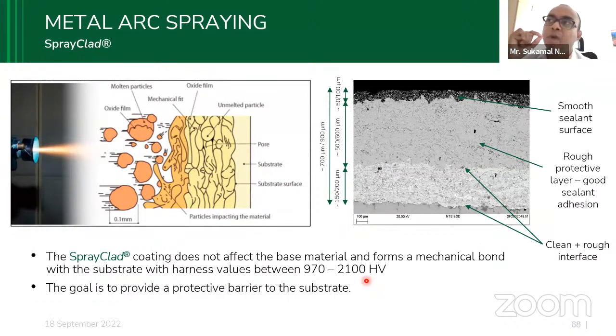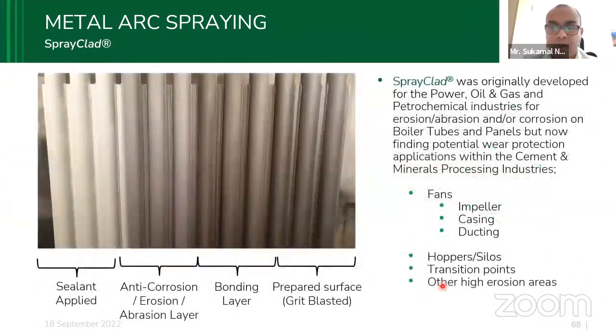Sometimes the customer doesn't allow deposition at a very high thickness, like 2 millimeters or 3 millimeters. If the customer needs it in microns, then we use this spray cladding technique. Our goal is to provide a protective barrier for the substrate. This is a very prominently used solution of spray cladding.